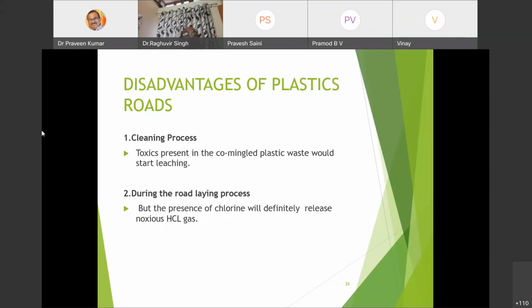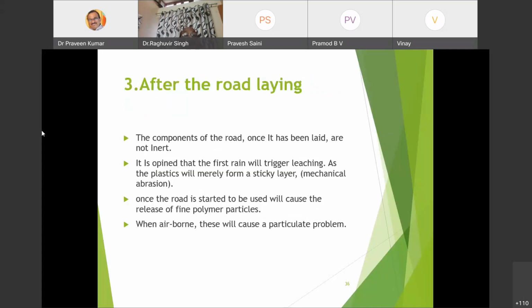Disadvantages of plastic roads: during the road laying process, toxics present in the commingled plastic waste would start leaching, and the presence of chlorine will definitely release noxious hydrochloric gas, HCl. After the road is laid, the components are not inert. It is apparent that the first rain will trigger leaching, as the plastic will merely form a sticky layer. Once the road starts to be used, mechanical abrasion will cause the release of fine polymer particles. When airborne, these will cause a particulate problem.